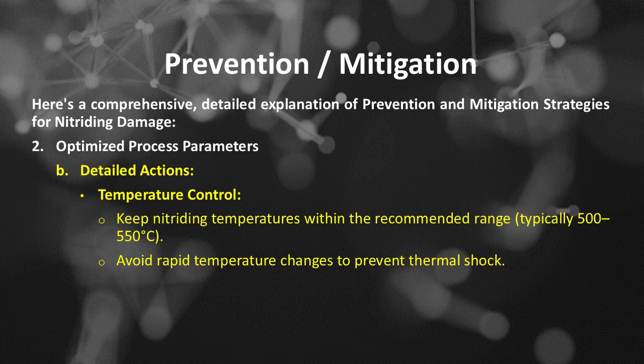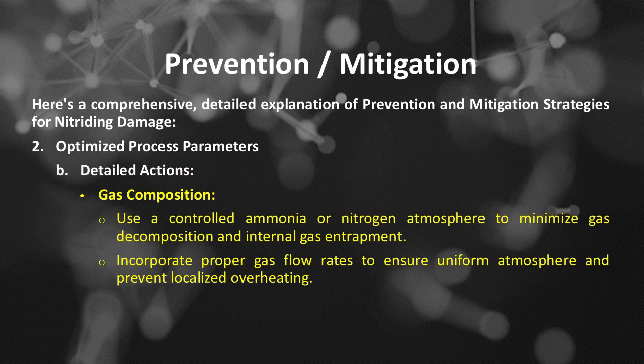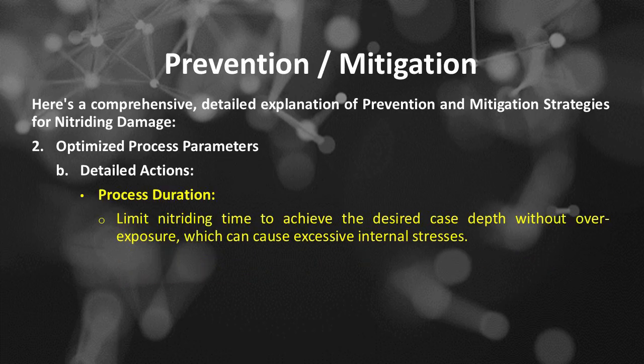Detailed actions in optimized process parameters include temperature control: keep nitriding temperatures within the recommended range, typically 500 to 550 degrees Celsius. Avoid rapid temperature changes to prevent thermal shock. The next is to optimize gas composition: use a controlled ammonia or nitrogen atmosphere to minimize gas decomposition and internal gas entrapment. Incorporate proper gas flow rates to ensure uniform atmosphere and prevent localized overheating. The next is to optimize process duration: limit nitriding time to achieve the desired case depth without overexposure, which can cause excessive internal stresses.